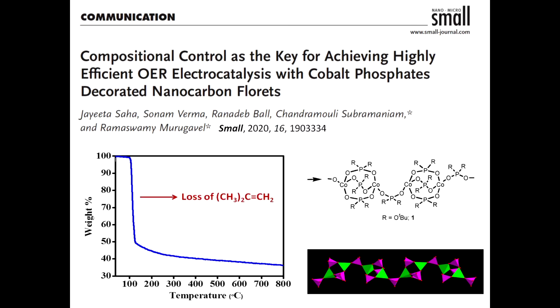As a result, there's no water like in the previous case. As you can see, at as low as 100 degrees centigrade, you lose all the organic content in one go in the form of isobutene and produce, at 150 to 160 degrees centigrade, a cobalt phosphate, which is Co(H2PO4)2. Then in this region, H2PO4 being metastable under those conditions, they cross-link and form Co(PO3)2. What you have at 300 is this Co(PO3)2.